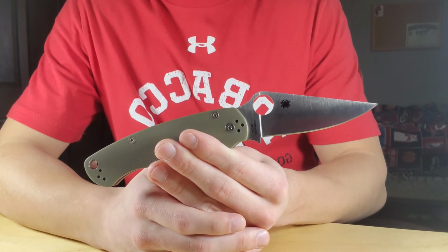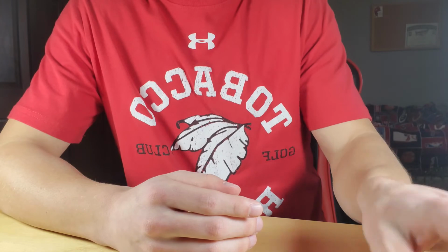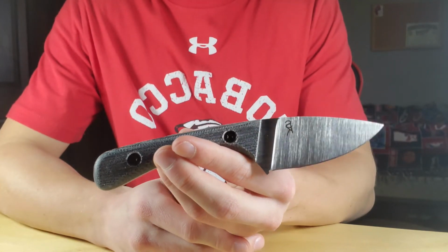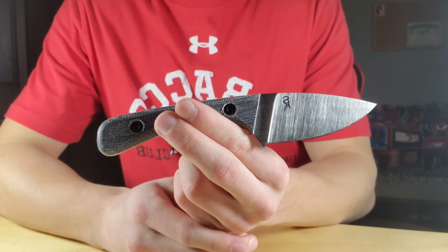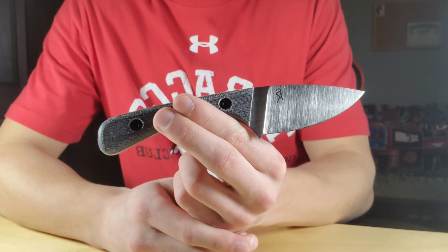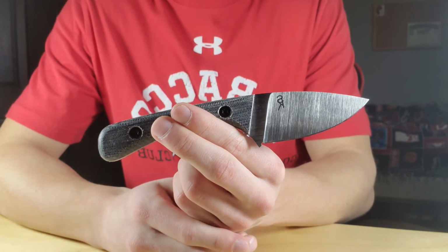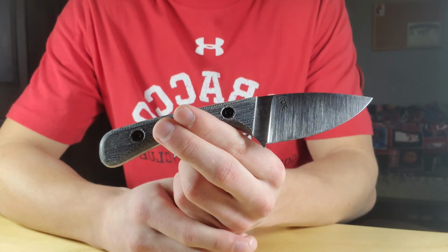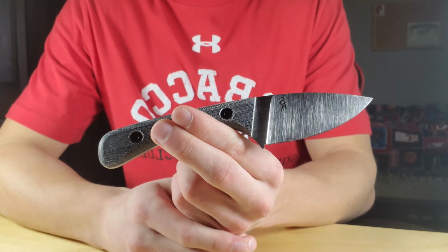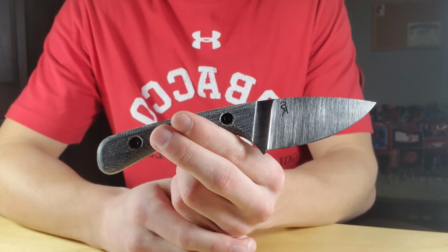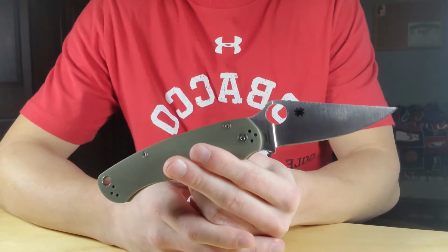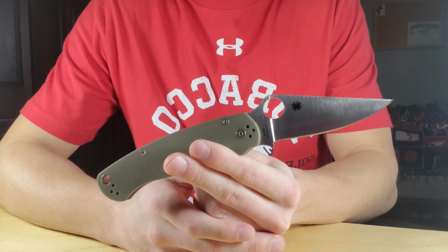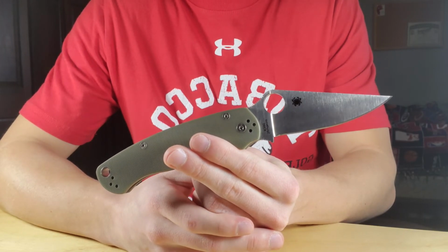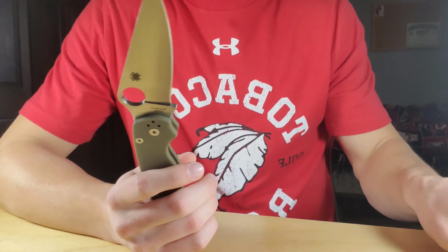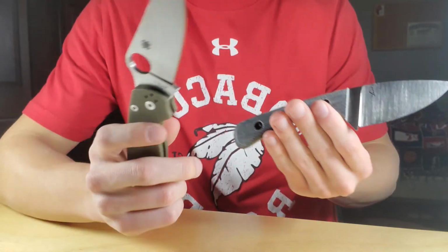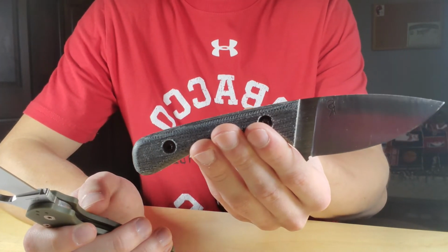It's a 13.5% difference, which may not seem like a lot, but the ease of cutting and sharpening is so obvious between the two. I actually had to sharpen this one up last night before I tested it. From start to finish, a 200, 600, 800, and 1,000 grit diamond progression took 5.5 minutes, which is stupid, at 13 degrees per side. The PM2 at 18 degrees per side takes over 20 minutes, which is 4 times as long to sharpen.